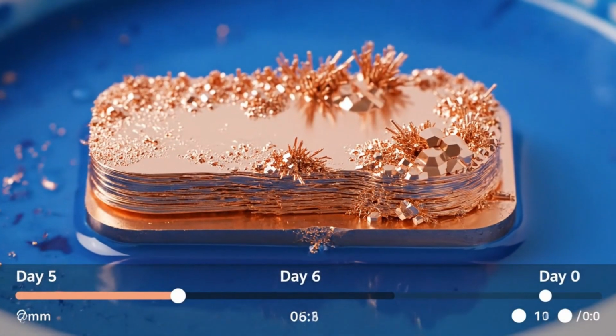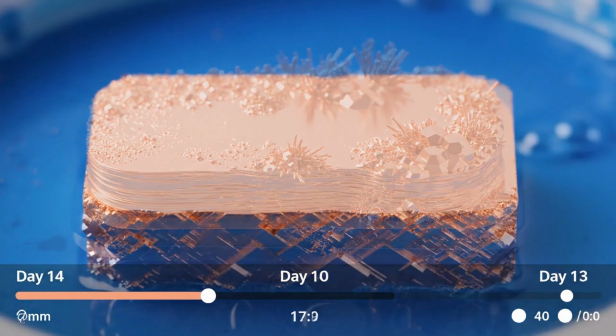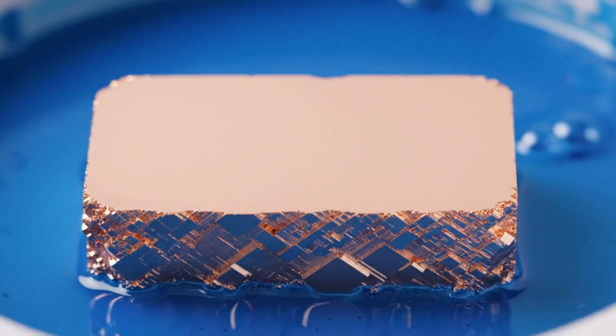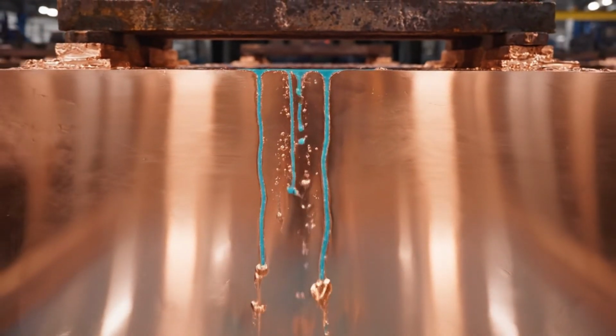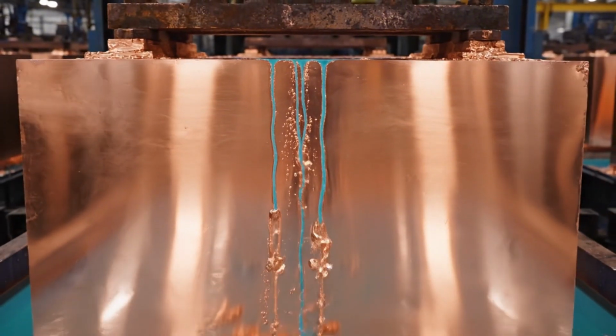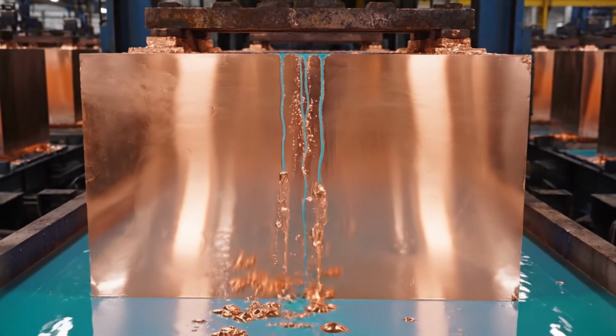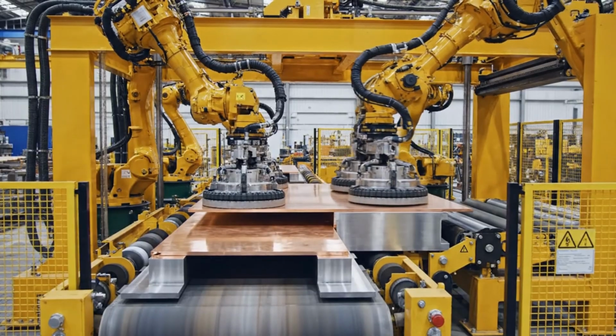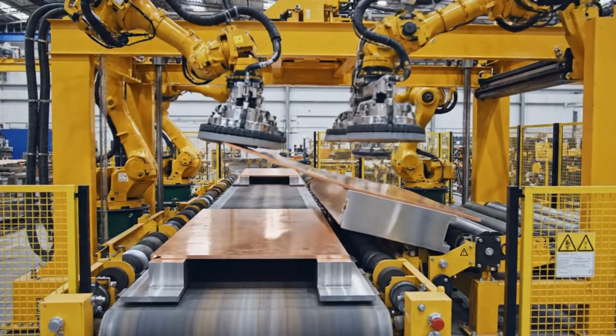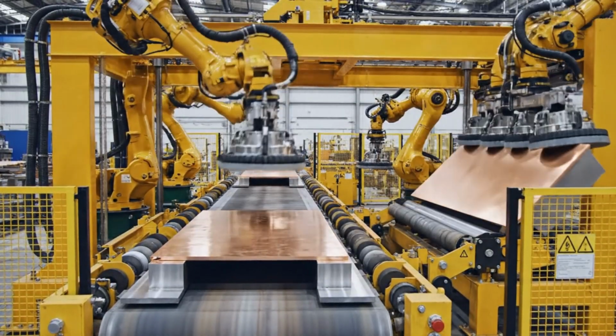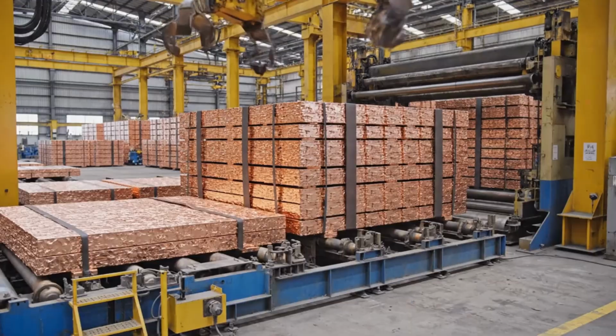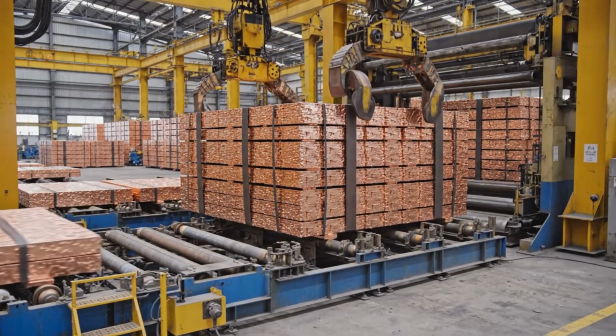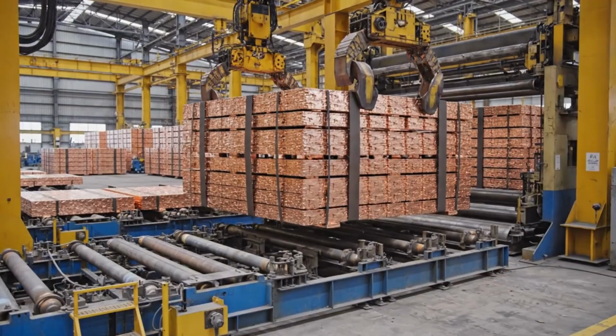Over 14 days, pure copper grows on each cathode, reaching 125 kilograms. 99.99% pure copper, the purest form commercially produced. Robotic stripping machines separate pure copper from starter blanks at 400 cathodes per hour. Cathodes are bundled for transport to rod mills and other copper product facilities.